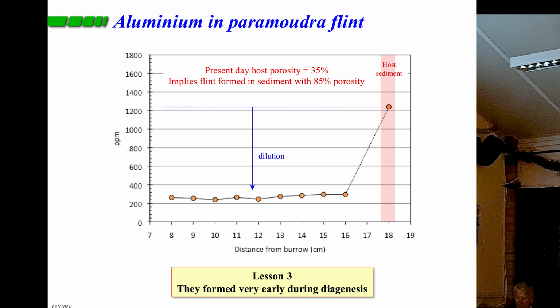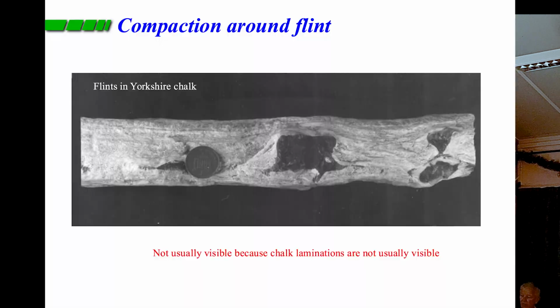And what you'll notice here is a huge dilution. So clearly this happened during quite early diagenesis. And in fact, if you go to somewhere where you can see the bedding in the chalk, this sample from Yorkshire, what you can see is that we often see compaction around the solid flint, which shows you that there was solid flint there very early during diagenesis.